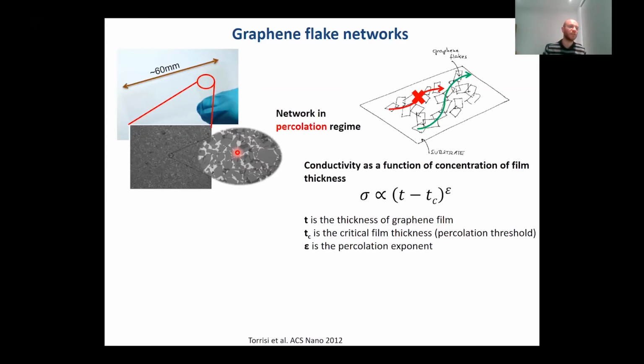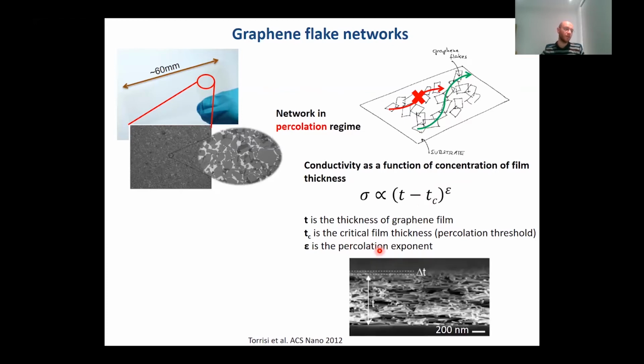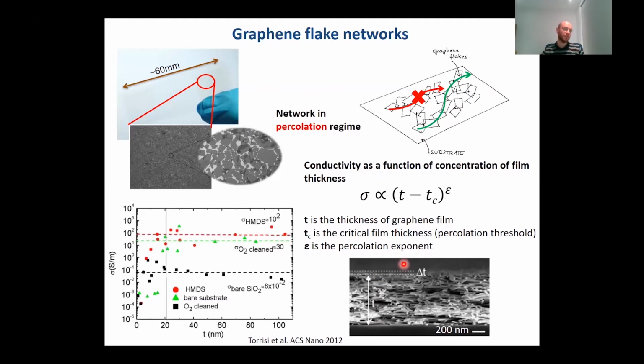So we need to consider that here the conductivity below a certain percolation threshold is dependent on the thickness. Particularly, you start having a linear dependence of the conductivity as a function of the thickness. This is a cross-section of a thin film above a certain critical percolation threshold, which we call TC. So you have a linear behavior, essentially, of the conductivity until it reaches a certain percolation threshold with a minimum thickness, where you have a bulk-like behavior, so a constant behavior of the conductivity.